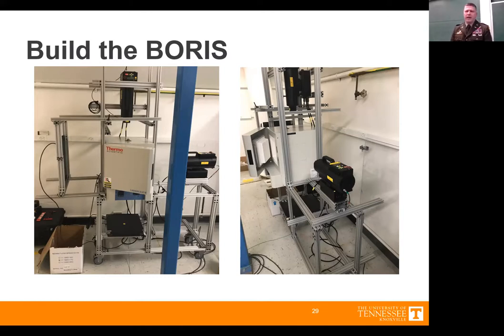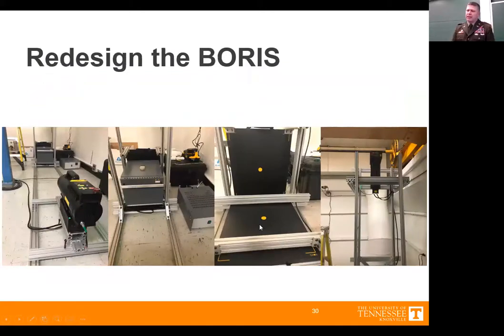It turns out, after running not very many tests, that it was very quickly determined that for these radiographs to be as usable as possible, with the best resolution, you really needed to get that panel as close as possible to the sample, and you really needed to get the X-ray generator as far away as possible. So I completely redesigned the system, and Boris ended up looking like this. There are two XRS4s, one mounted on the floor, firing up through the front of the furnace. The second XRS4 is mounted approximately the same distance up in the air, 6.5 to 7 feet, aimed down, firing through the top of the furnace.